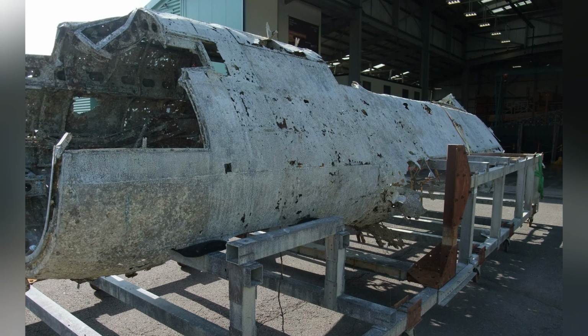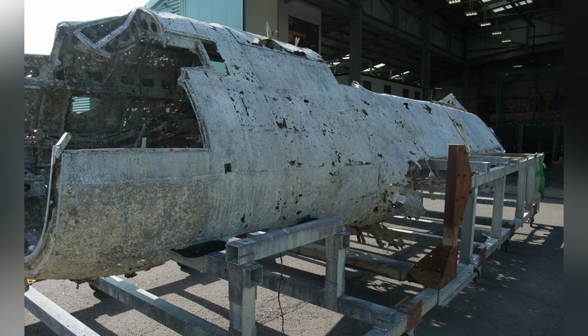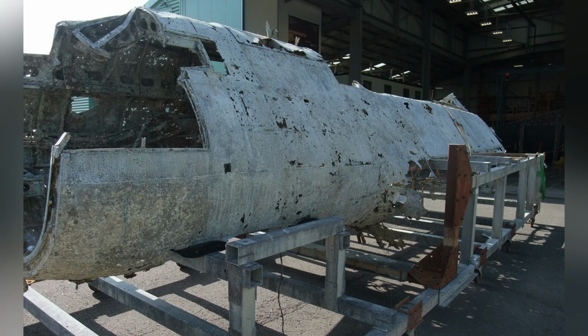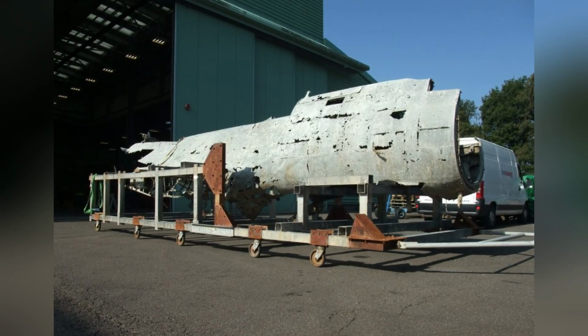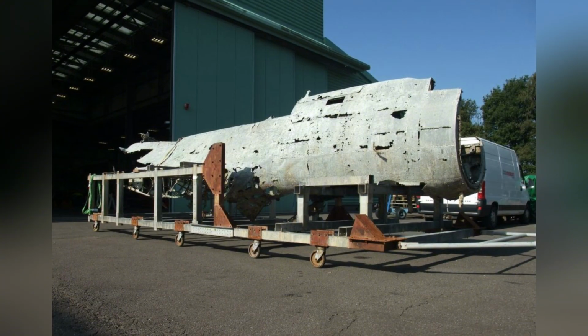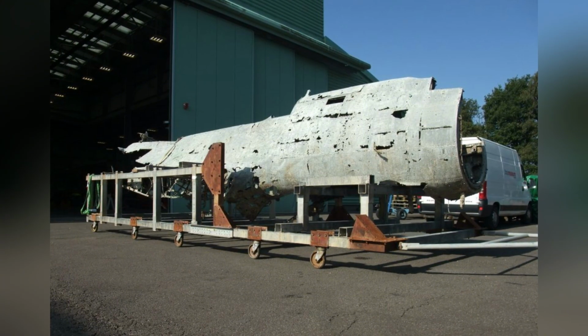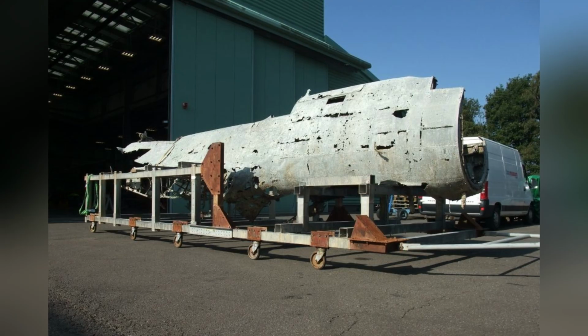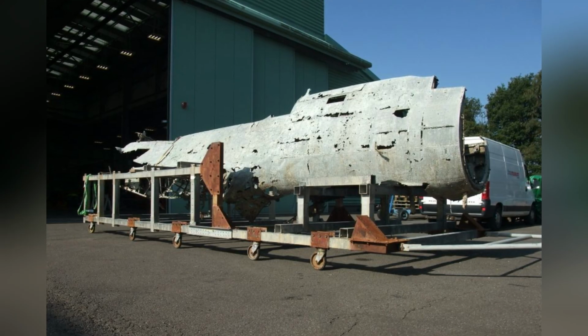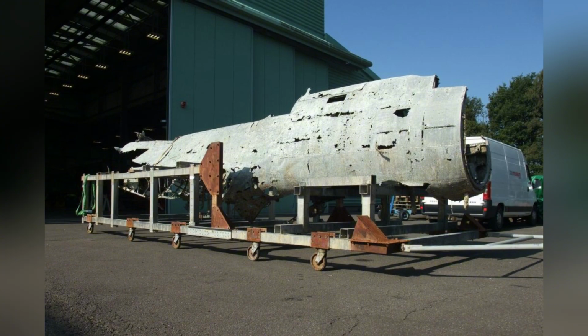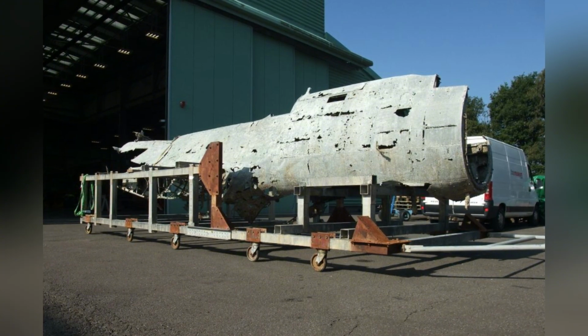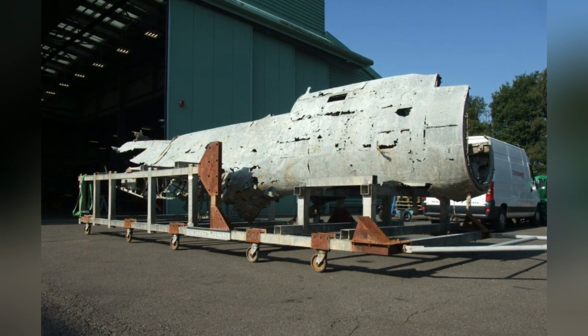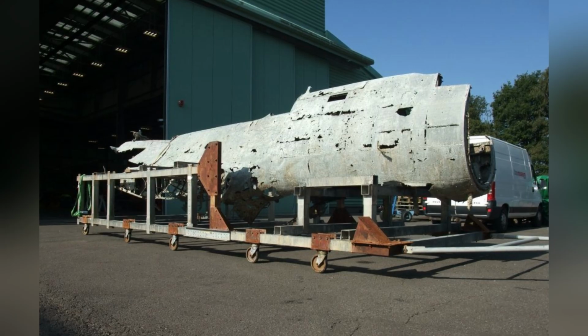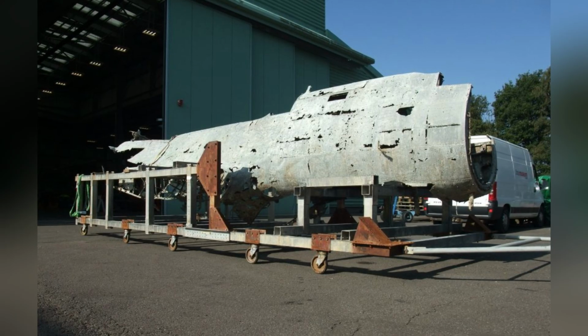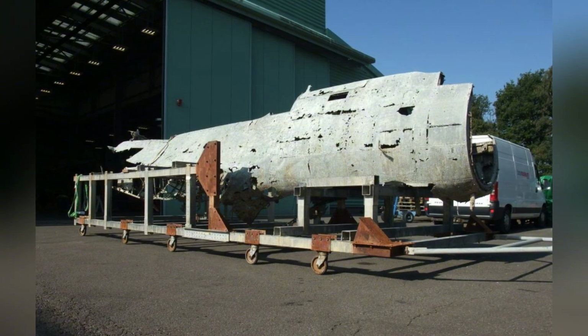The success of the operation is measured not by the gloss of the paint, but by the stability of the structure. The recovery proved that it is possible to retrieve a large, fragile composite object from a high-energy tidal environment and transition it to a stable museum setting without catastrophic loss. The Dornier Do 17 serves as the only physical reference point for a type that once numbered in the thousands. The legacy of the project lies in the geometry of the lift and the chemistry of the tunnel.